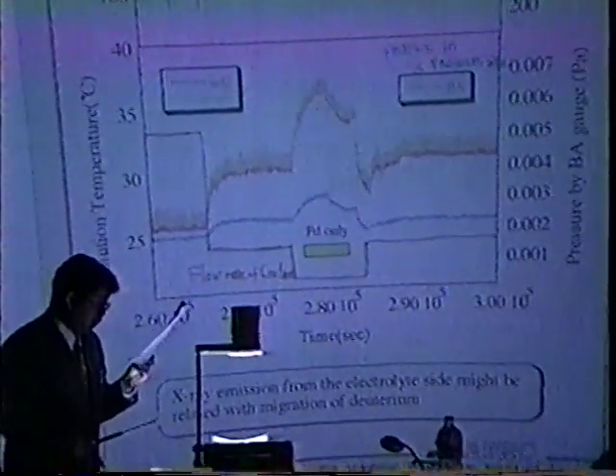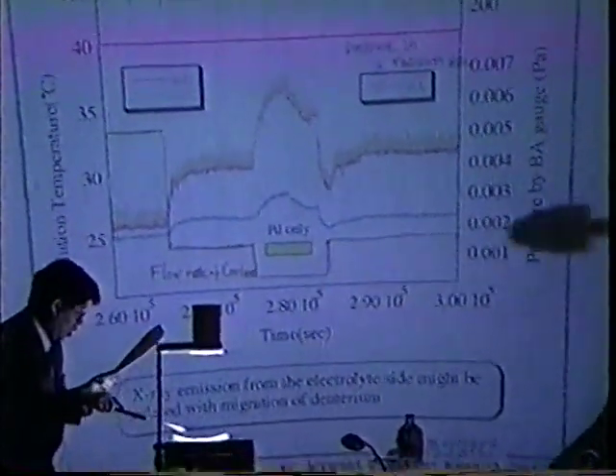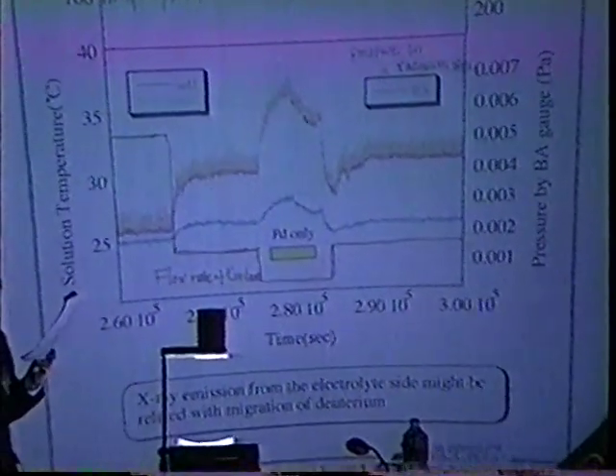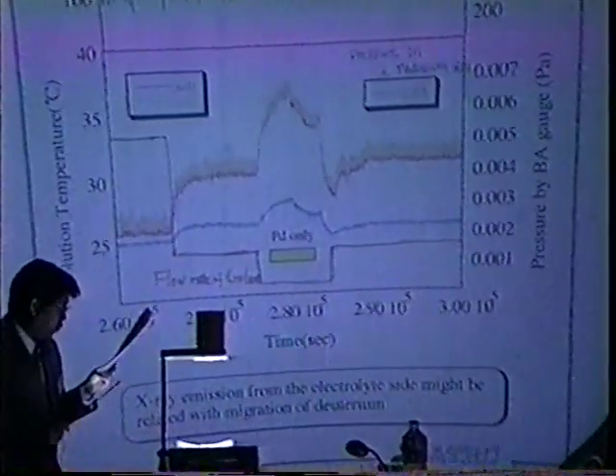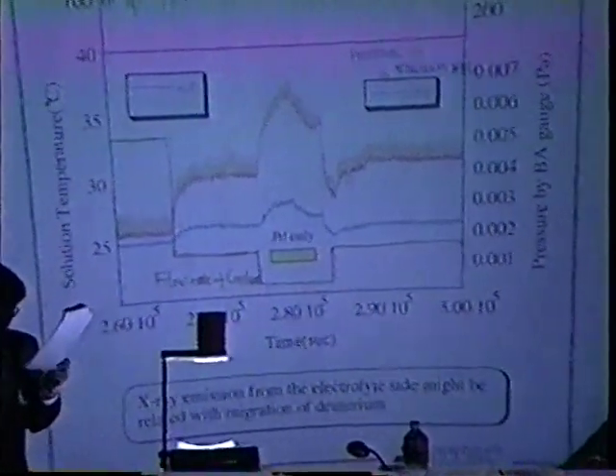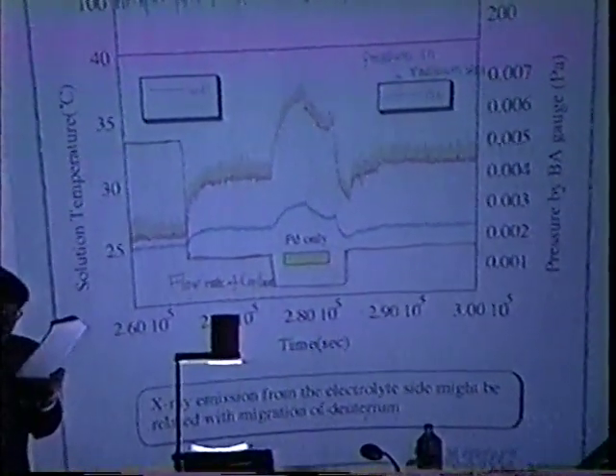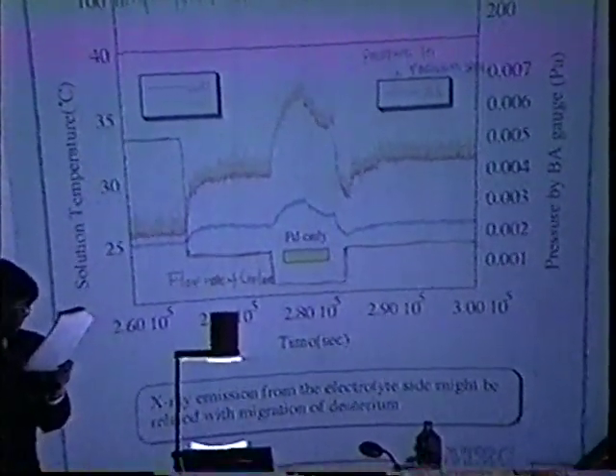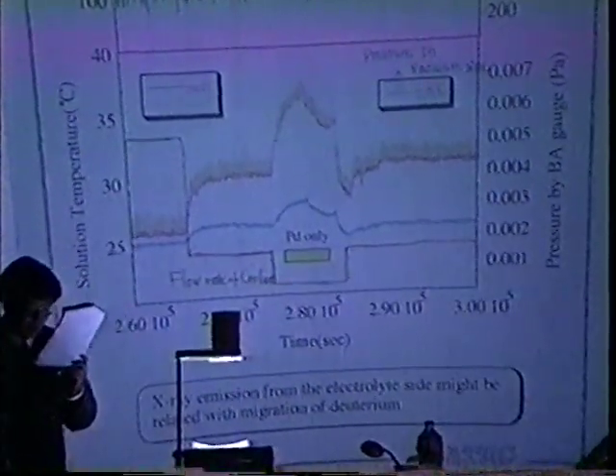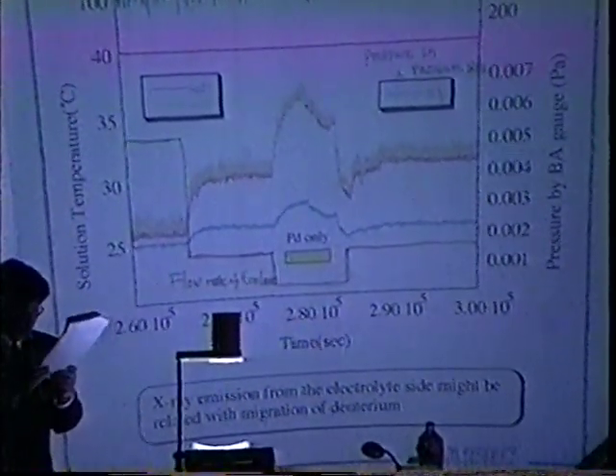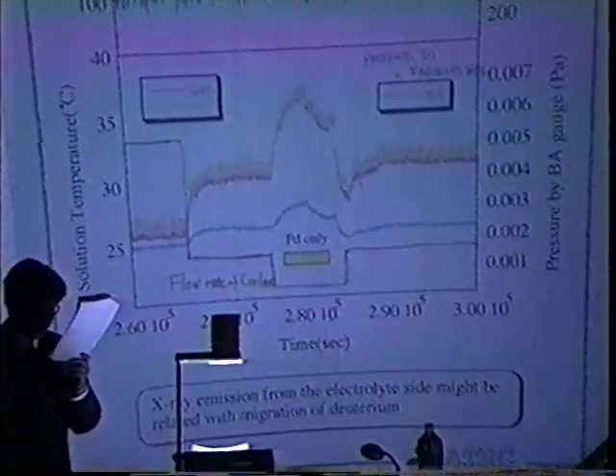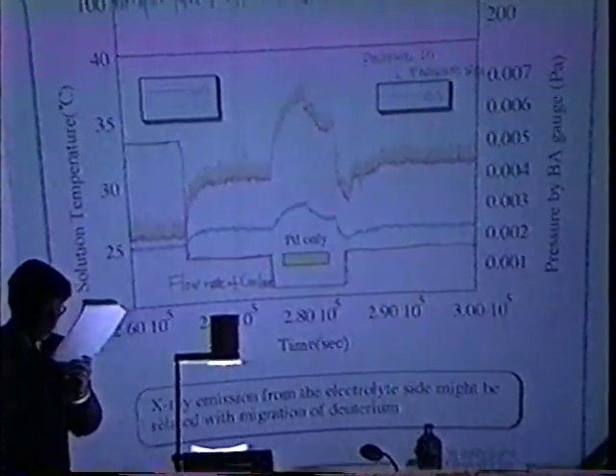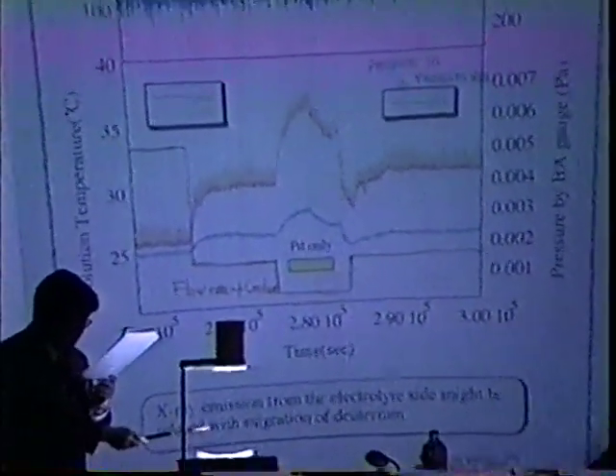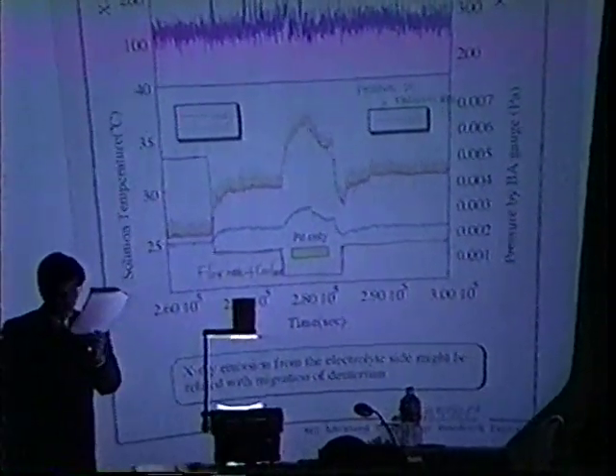In this case, we change the flow rate of coolant like this. If we change the flow rate of coolant, then temperature of palladium is changed, and migration of deuterium is affected. Therefore, pressure in vacuum chamber can be changed. Based on these experimental results, it seems that X-ray emission is related with the migration of deuterium in palladium.